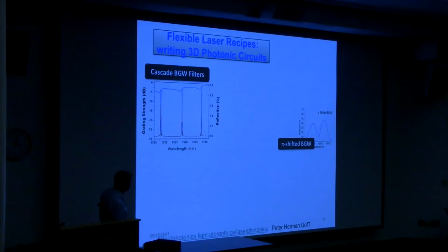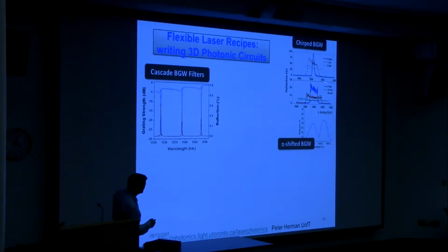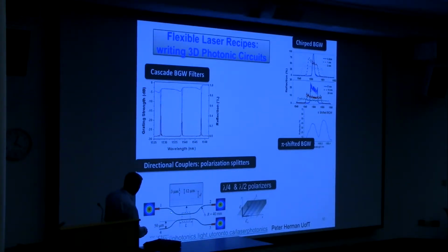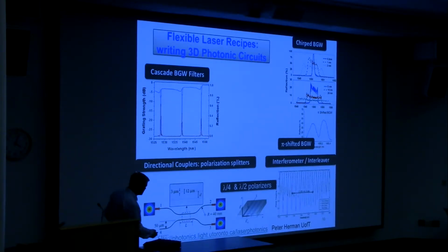It's a 3D process, and we did things like chirp the spectrum, which is important, say, in telecommunication applications. We narrowed them with pi shifts. We added features to make birefringent effects, and so we showed quarter wave and half wave polarizers. If you bring the waveguides close together, they act as directional couplers, so you can switch light from one path to another path, which would be wavelength sensitive. And so these are well-known optical effects that have been applied in fiber and in planar circuits, and we showed here's a way to make them inside bulk glass without any multiple step processing, and some examples of the spectrum, say of a cascaded Mach-Zehnder interleaver, for example.